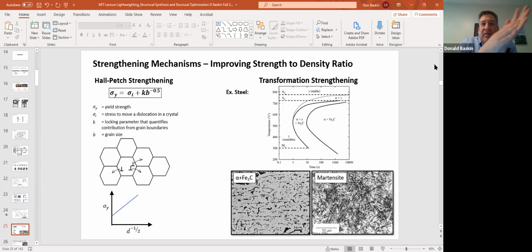The theory goes that if you have a lot of small grains, you have a lot of grain boundary area, then it takes a lot more energy to get these dislocations to go over these grain boundaries. That, again, is an increase in yield strength. This mechanism, Hall-Petch strengthening, is a common way of strengthening steel. If you see a steel that has niobium additions, or columbium, they also call it, this is exactly what they're doing. They're decreasing the grain size in order to increase the strength.